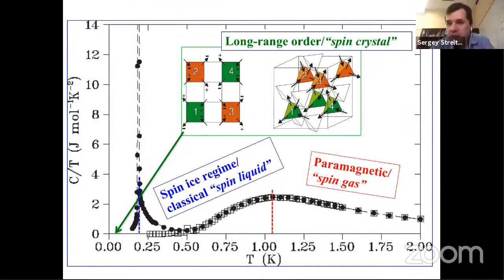So is all this because of dipole-dipole interaction? Yes, it's all dipole-dipole. But the dipole-dipoles get screened somehow by very interesting physics, which means that if you go back in the model and you refine the corrections in the model, not just nearest neighbor exchange, but you start to add second or third nearest neighbor, you can change that ground state, because the energy between these states is very finely balanced.